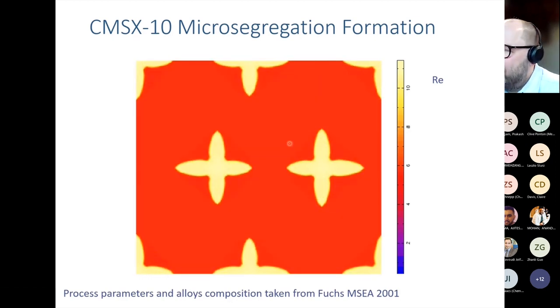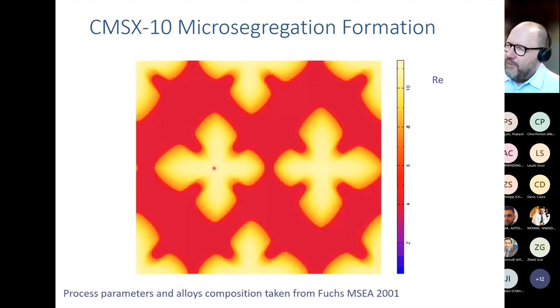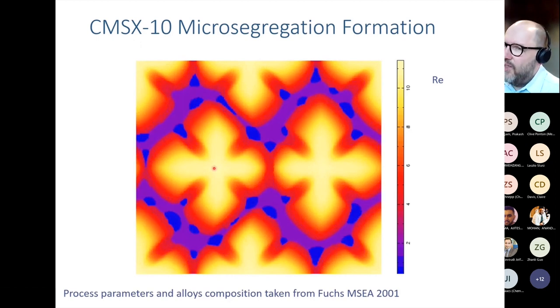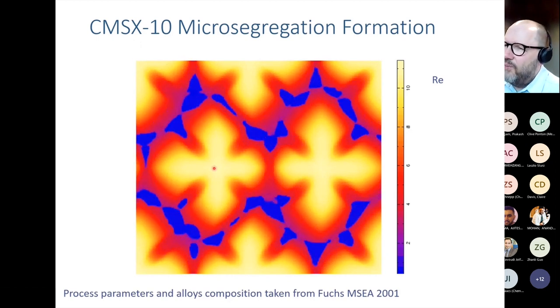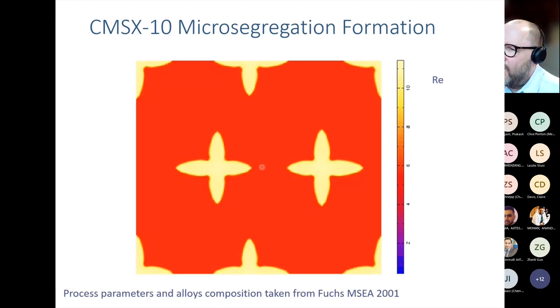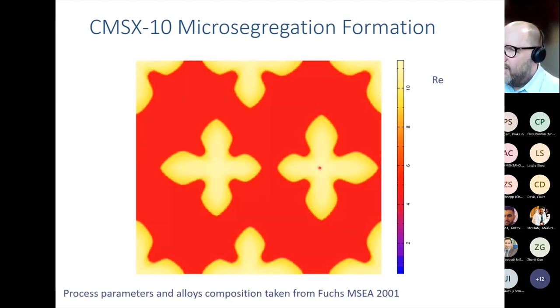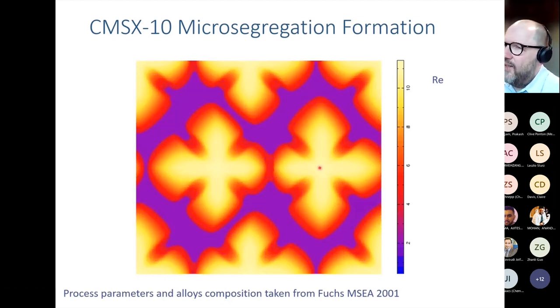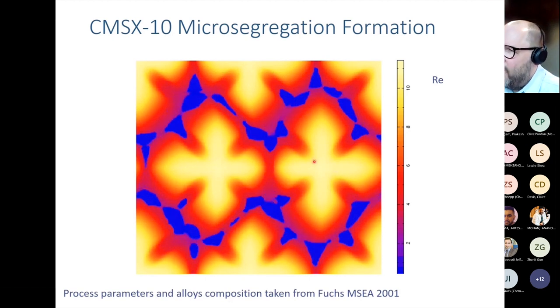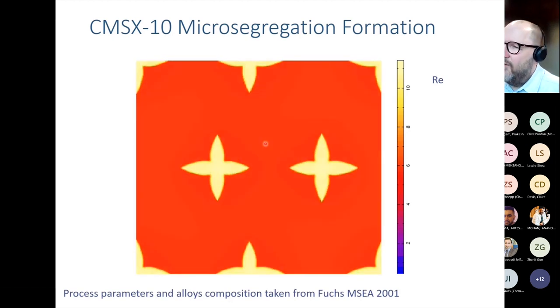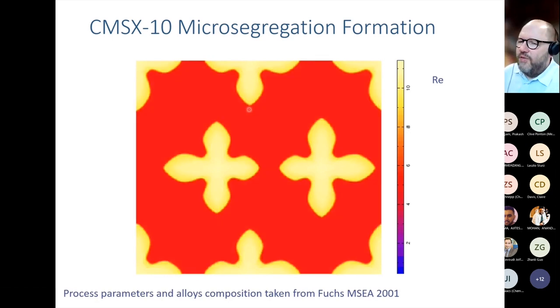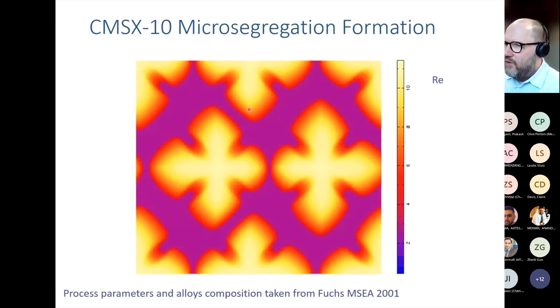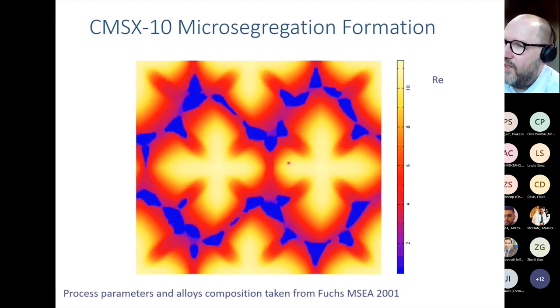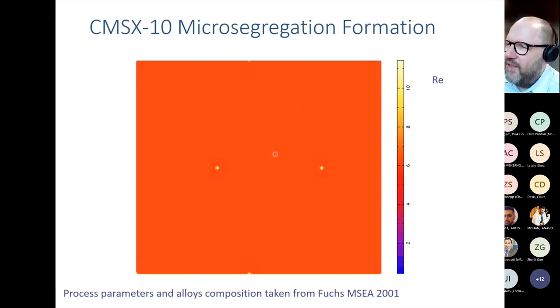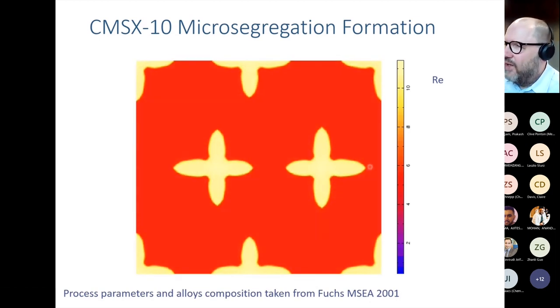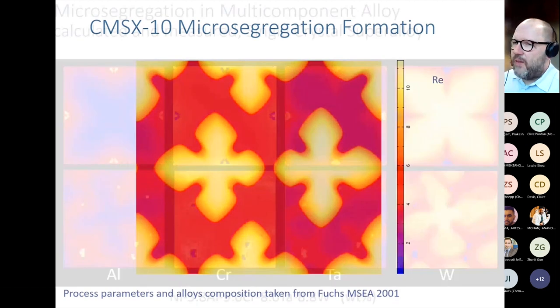And so we look at the cross section of a directionally solidifying dendritic array. We have a number of dendrites in there. We initially see the dendrites growing. These were the positions of the dendrite tips. Then the growth in the cross section, forming side arms, enrichment of rhenium inside the dendrite core, and then finally nucleation of the gamma prime phase, which is then forming these blue dots at the end of the solidification and decorating the dendrites and the microstructure.